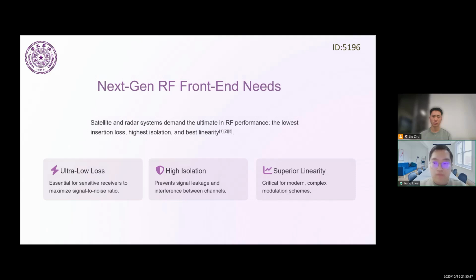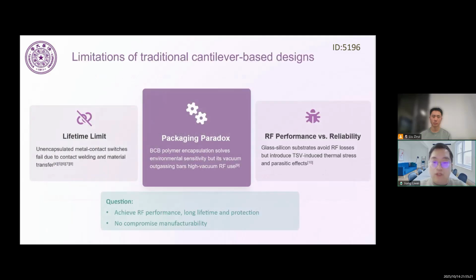But here's the problem. Traditional cantilever-based RF MEMS switches, while promising, have some serious limitations. First, reliability is a big issue. Unprotected metal contacts can weld together or suffer from material transfer. And if the switch is left exposed, it's vulnerable to dust, humidity, and even mechanical shock.